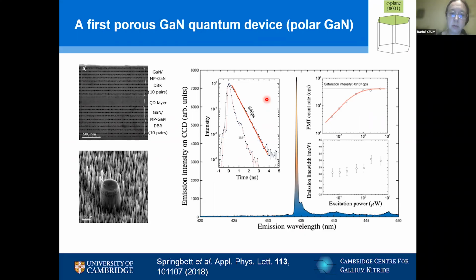But that's not actually a showstopper at all for the dislocation-based etching technique, because we can etch fields that are like tens of microns across. Most of the materials I'm showing here have dislocation densities in the 10^8 to 10^9 regime. But if we took the dislocation density down to the 10^7 or the 10^6 regime, it would still work. It gets to be a little bit more tricky when we get down to 10^5. It's still just about workable, but there's hardly any gallium nitride that's like that anyway, sadly.